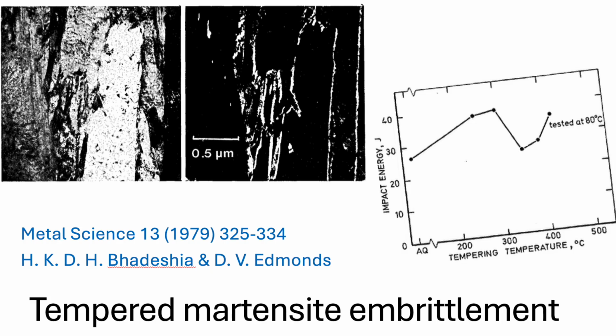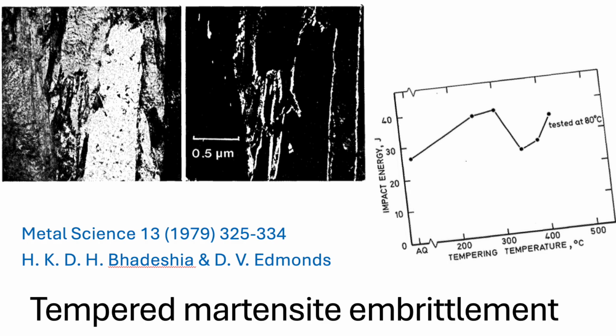The later parts of this study are fascinating because they introduce two contrasting alloys. And these prove that while the result, brittle fracture linked to intralath cementite, seems consistent, the cause, the trigger that creates that cementite, can vary dramatically based on the specific alloying elements used in the steel. Okay, tell us about these contrasts. What changed when they swapped out the molybdenum, for example?